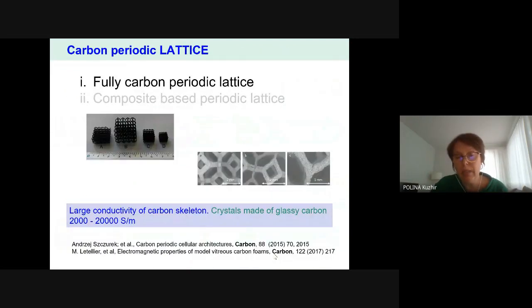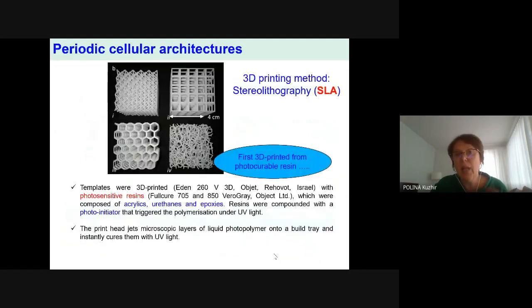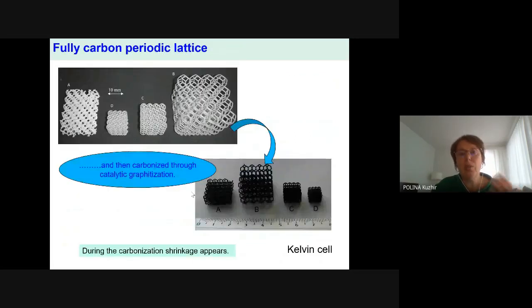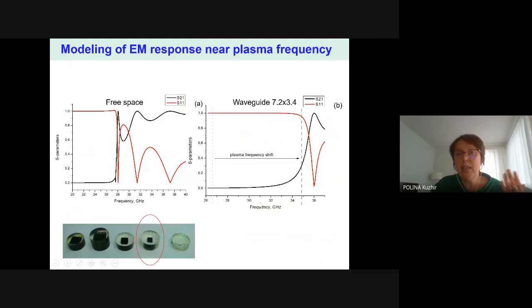So for the fully conductive skeleton, normally people use 3D printing—stereolithography—and when you impregnate this beautiful structure with some catalyst and pass it through pyrolysis, you could carbonize the structure. During carbonization, shrinkage could appear, and this lattice will not be fully symmetrical anymore. This gives us the idea of using this material as a photonic crystal.